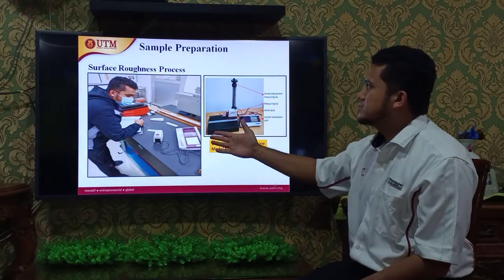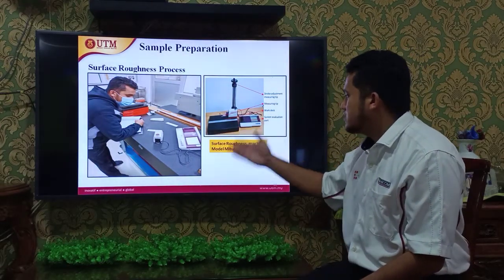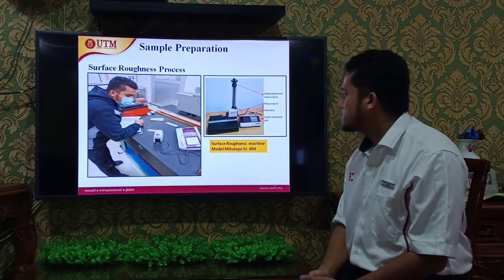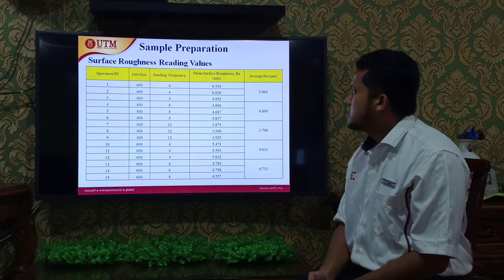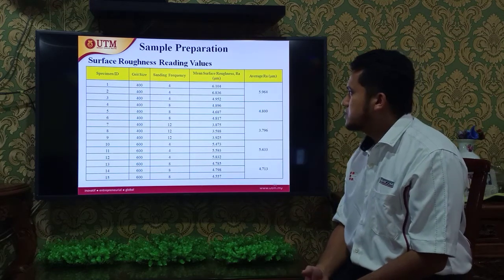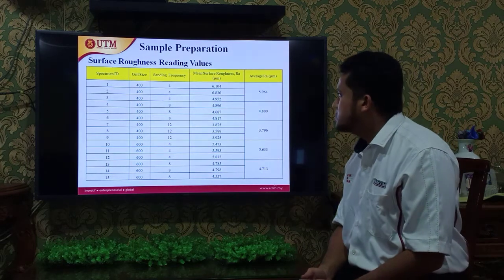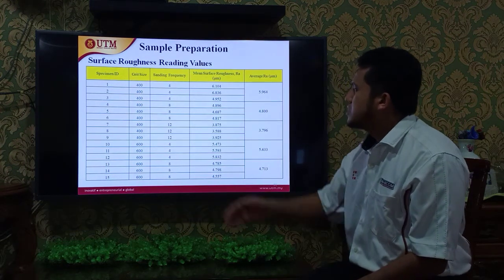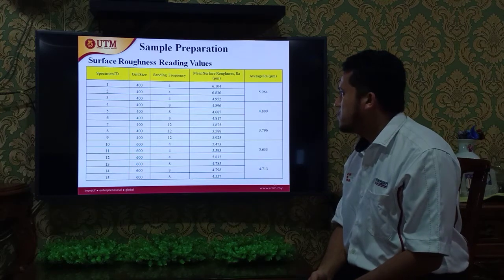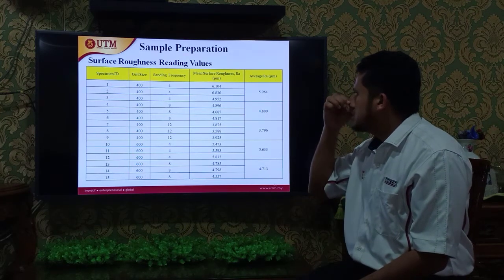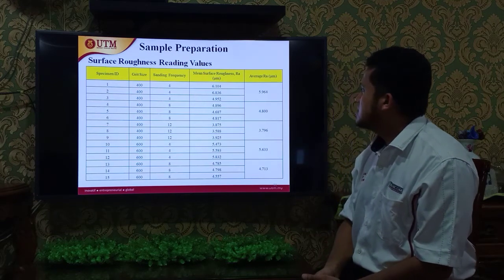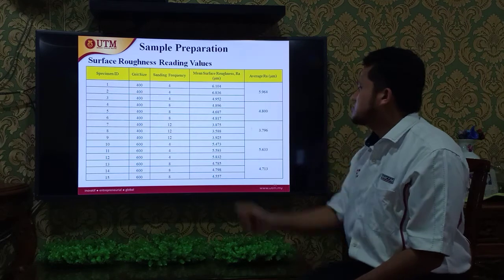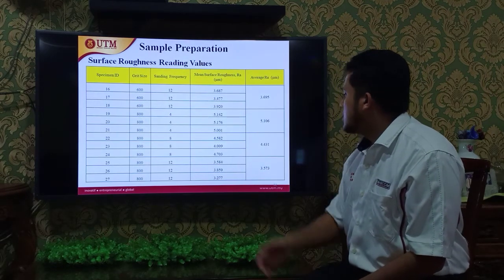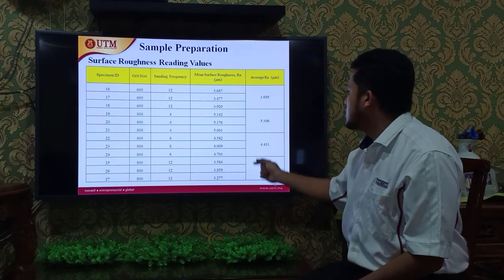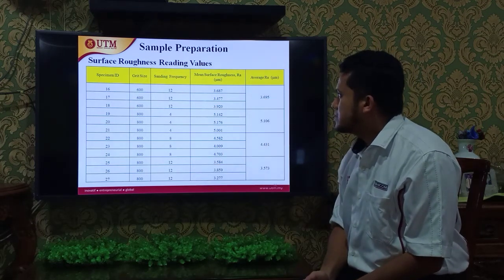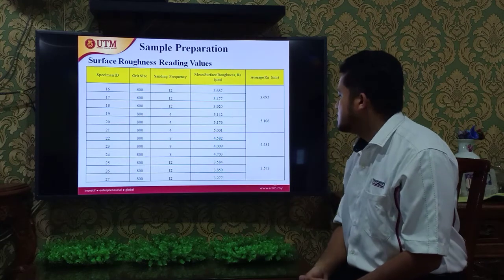This is the surface roughness activity. I use the surface roughness machine model Mitutoyo SJ-400. After we do the surface roughness activity, we get the reading values. For grit size 400 with a sanding frequency of 4 times, we get the highest average surface roughness, which is 5.964, and the lowest surface roughness reading value is for grit 800 with 12 times sanding frequency, 3.573.